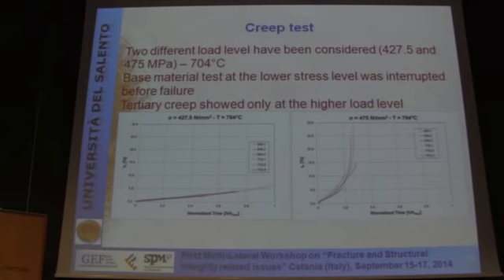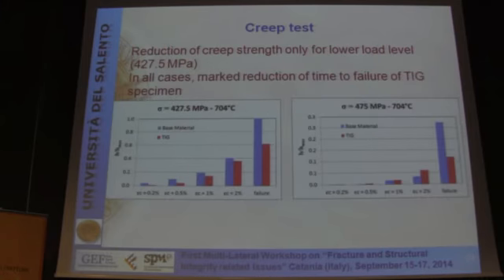The curves of TIG welded specimens are practically coherent with the base material, and effectively, if we compare the time to reach a fixed creep deformation for base material and TIG material, it is practically coherent. The exception is the failure. In the case of failure, we observe a strong reduction of time to failure at both load levels.